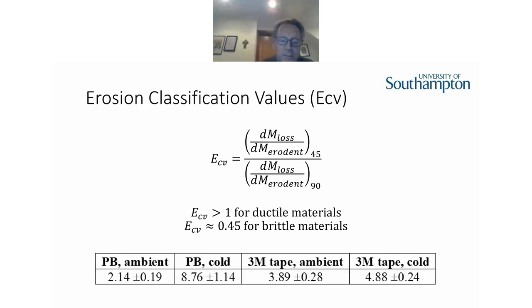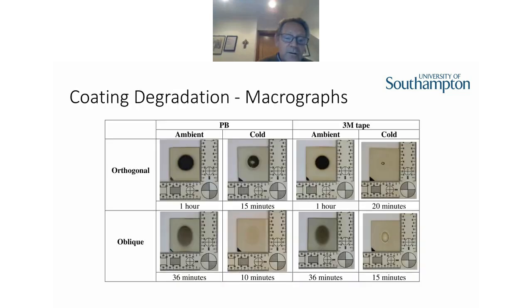And obviously we were anticipating some increase in brittle behavior as you go down in temperature, but we didn't actually see that. As you can see, the numbers are quite high for both systems. They go higher, so they're way above 1. So there is an increase in ductility from the cold mass loss rates compared with ambient. So that was interesting.